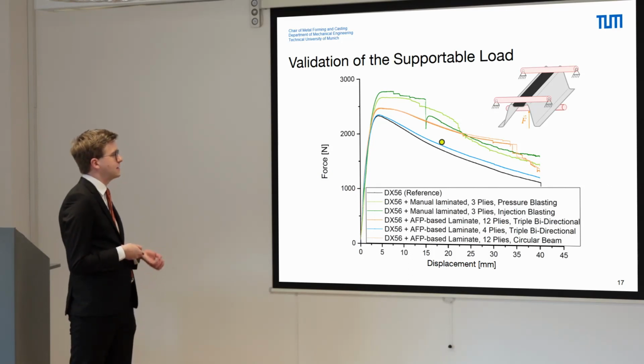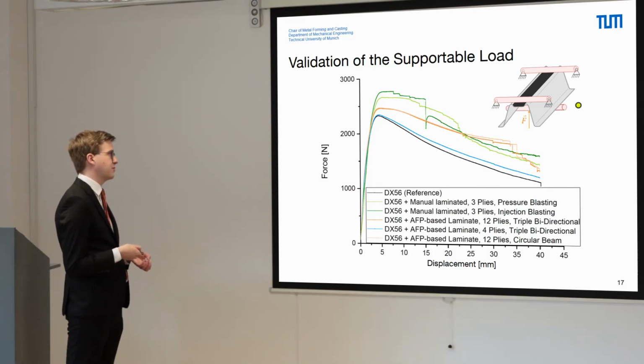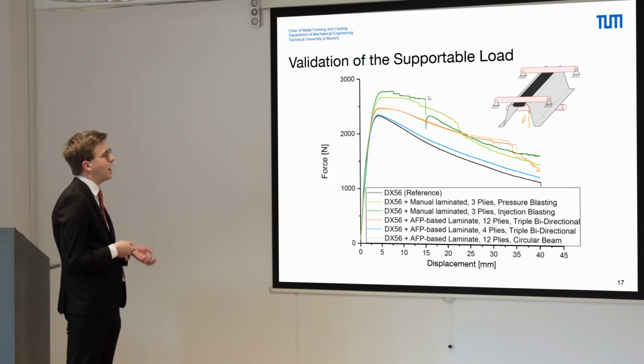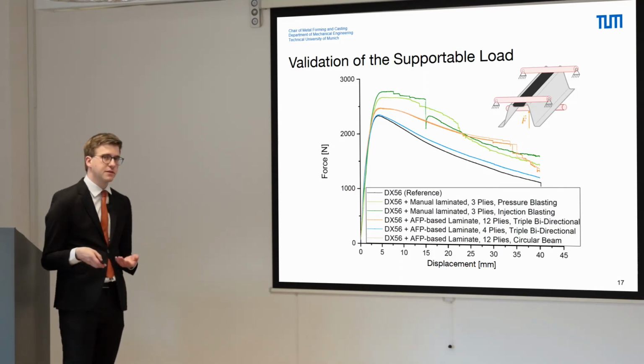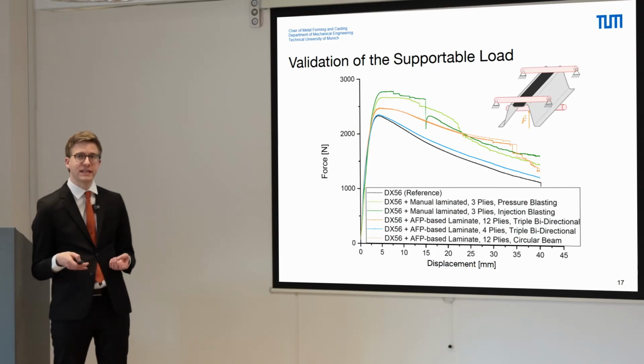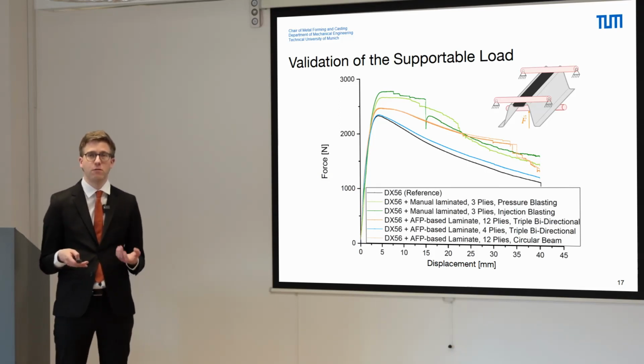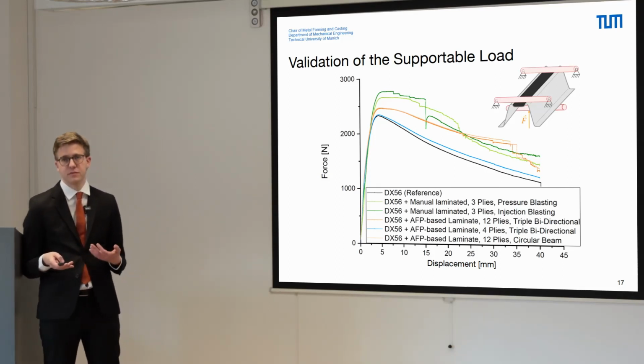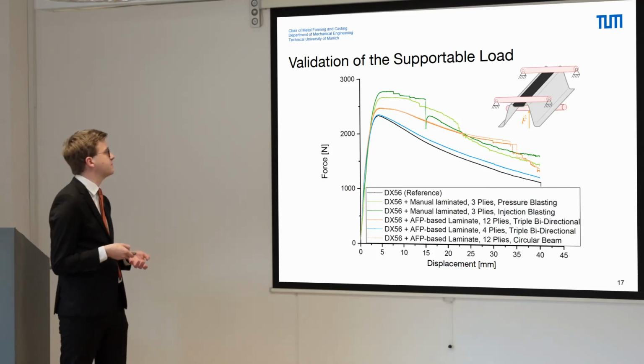As the results from this figure and from this experimental investigation show, there's an increase in the supportable load in the three-point bending test, and the amount of the increase is dependent on the thickness of the reinforcement structure. So we fulfilled this necessary condition for the manufacturing of load-dependent sheet metal components.